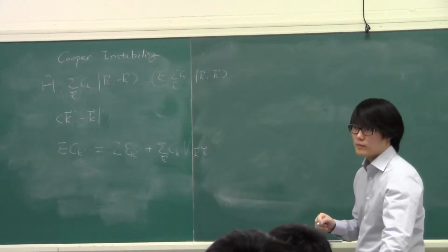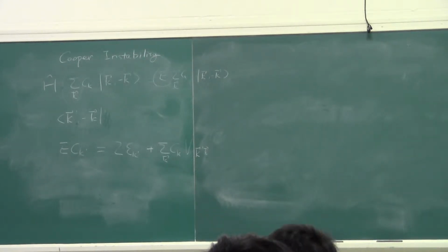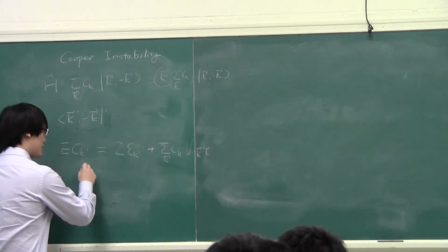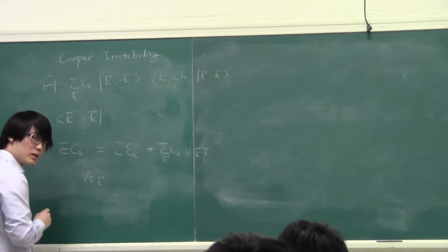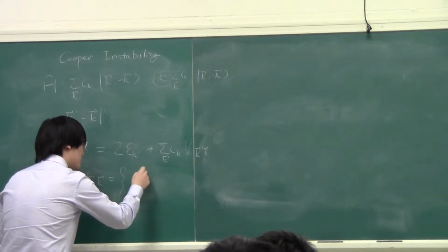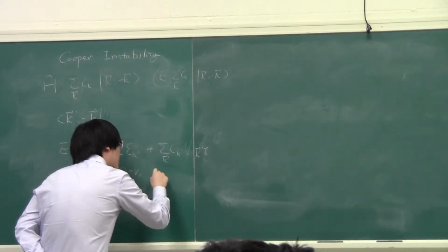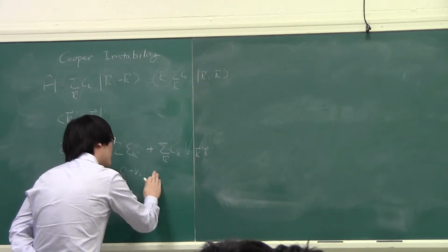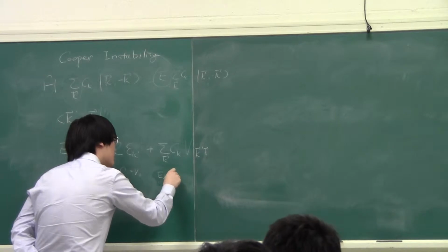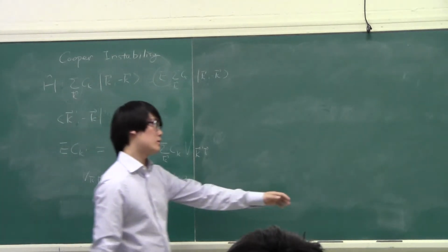Okay? And because in the Bardeen-Pines interaction that we roughly talked about here, we saw there was a possibility for an attractive interaction. And to simplify the equation, to simplify the algebra as much as we can, I'm going to say that in the problem at hand, we're going to take this to be 0 mostly, and then to be non-zero, okay, to be a constant, an attractive constant, between the range of the Fermi energy plus minus h bar omega D, the highest energy of the phonons, which is what we talked about over in the first part, right?